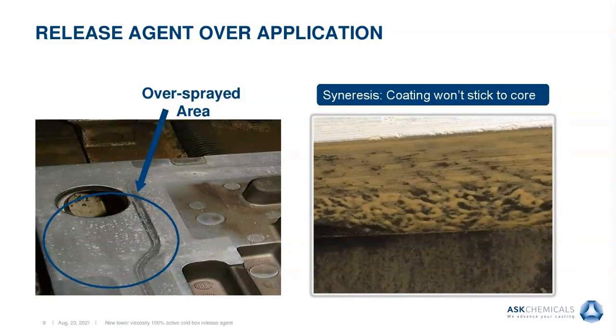Particularly Harbor Freight has spray equipment that typically would be used for automotive painting that you can use that have smaller tips. We recommend 20 to 30 thou for the 100% active release agent so that you don't over apply it. Typically with a solvent-based or water-based release agent, you might be able to get away with a larger tip size. But with the 100% active release agents, you want to use a smaller tip to help you from over applying it. Okay.